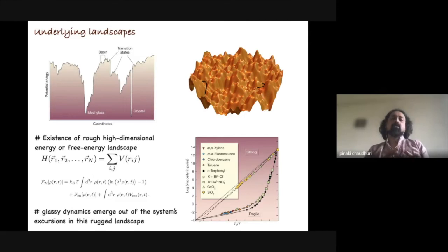Whatever structures we observe at rest are mostly structures at the local minimum or minima of this energy function. In glass forming systems, this energy function, or a free energy function, which is written at the bottom, in this high dimensional 3n dimensional space has a very rough structure. In the schematic diagram on the top left, you have a rough landscape where you could have a crystalline minimum, or an ideal glass minimum, which may or may not be realizable. But locally, you have multiple minima which scale with the system size. The larger the system, the more such local minima.